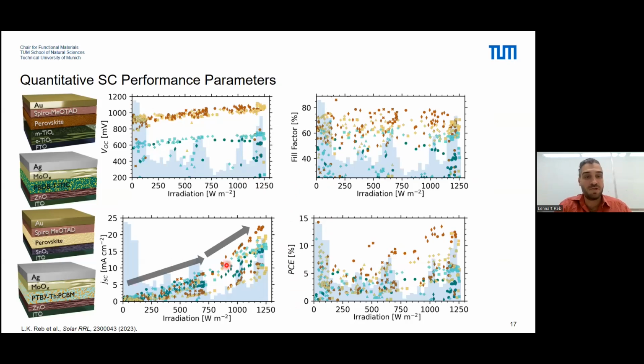Here we have the short circuit current. Here we see an increase, but there's a curve. This curve can mostly be attributed to the fact that for high solar inclinations, we have some shadowing, meaning that at lower irradiations, not the entire cells are illuminated. Then for the VOCs, we see slightly different trends. For the perovskite solar cells, the VOC increases with irradiation. For organic solar cells, it levels off, starting at intermediate irradiations. Just as a remark, classical testing conditions are around here, 1000 watt per square meter.